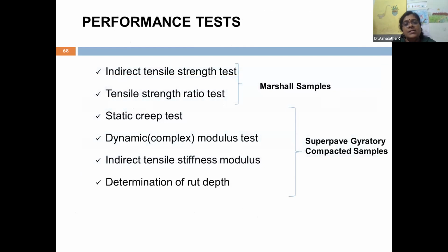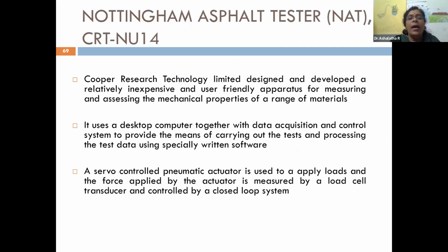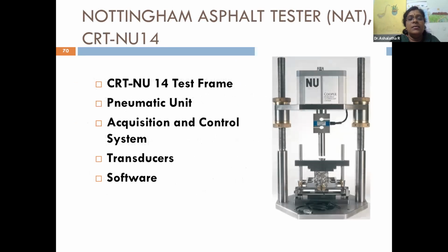And then what we did is that on the samples which we have finally, sample 1 with 2% Sasobit and sample 2 with 0.8% Sasobit, we conducted various performance tests. So indirect tensile strength ratio test, static creep test, dynamic modulus test, indirect tensile stiffness modulus determination, rut depth, etc. were done. In the first 2 cases, Marshall specimens were cast, and for the others, Superpave gyratory compacted samples were prepared. This is the test setup which we used, I'm not going into those details.